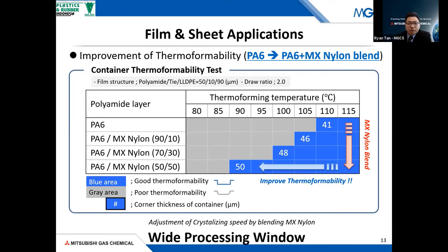Next, in the films and sheet application, MX nylon has also been used to improve thermal formability of a nylon 6 tray. So if you notice, normally for barrier trays, it is usually made up of three different materials, and one of the common materials is nylon 6. As a plastic processor, it is known that with increasing number of layers, the difficulties in producing such products increases due to the tightening of processing windows. However, with the use of MX nylon in this case, we have been able to widen the processing window for thermoforming by reducing the temperature of thermoforming as shown here, from 115 degrees down to maybe 90 degrees, depending on the dosage of MX nylon that you use.